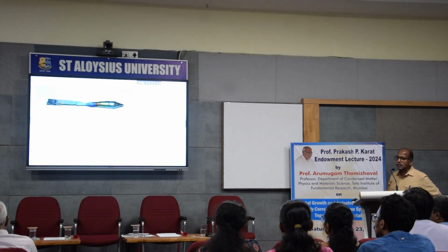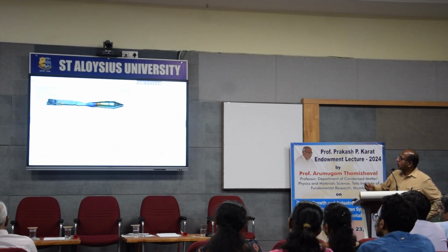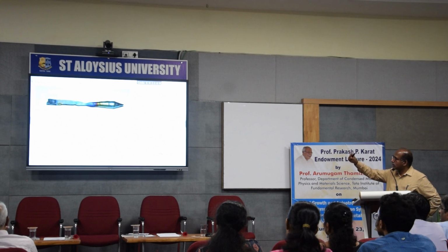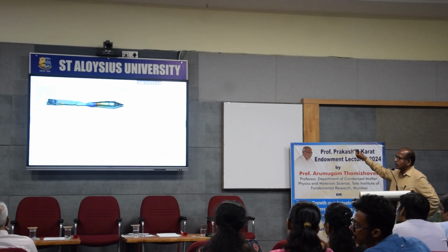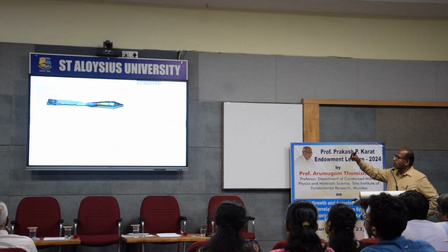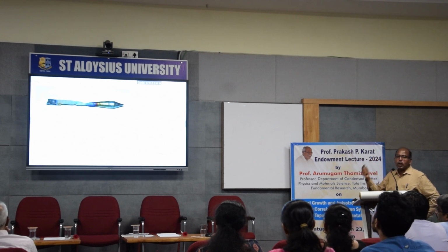And this is one of the crystals which we grew a very long time ago. We used a polycrystalline seed, and I can see that at the center there is a very small diameter, and then the diameter increases. This small diameter is for necking. I select only one grain to grow into a larger crystal there.